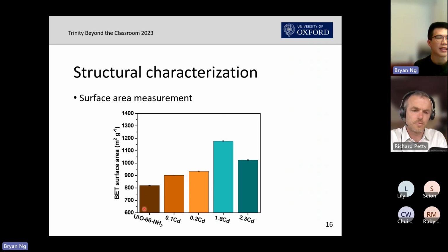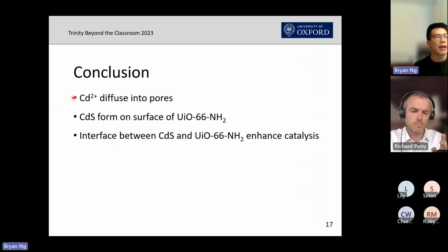And then these are the samples that we ended up with. These are the data. We have a very good correlation with the 1.8 and 2.3, where you have the optimal point on the 1.8 sample, and less so in the 2.3 sample. With these data, we can briefly conclude that you have the cadmium 2+ and the sulfur that diffuse into the pores, and also cadmium sulfide that is formed on the surface of the UiO-66-NH2, which is the name of the MOF. And we can see that it's the interface between the cadmium sulfide and the UiO-66-NH2 that is